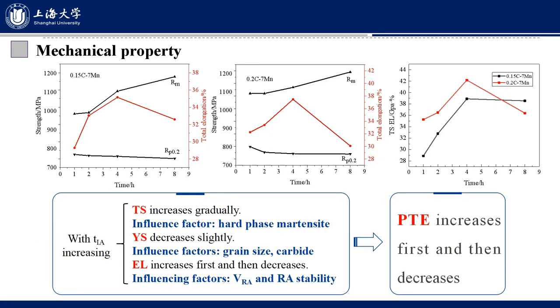This slide shows the mechanical properties of the steel for different intercritical annealing time cases. With intercritical annealing time increasing, tensile strength increases gradually, and the influencing factor is hard phase martensite. And the yield stress decreases slightly. Influencing factors are grain size and carbides. And the total elongation increases first and then decreases.